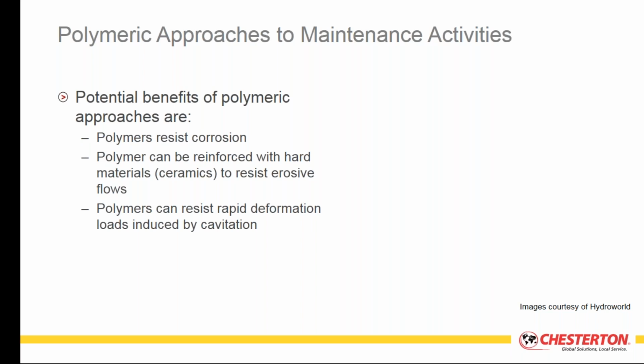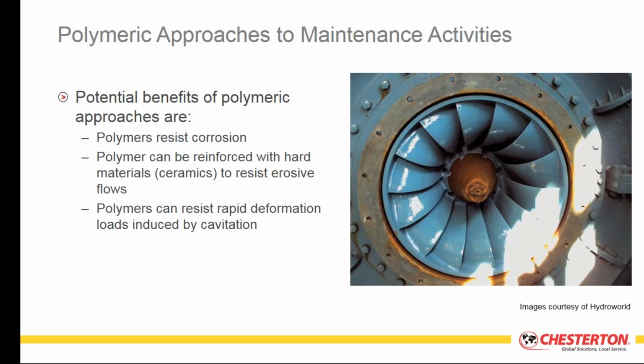However, if cavitation is relatively slow and progressive, you may be able to use a polymer-based compound quite successfully to address and repair those zones of cavitation, with the understanding that when you come back on a maintenance cycle 3 or 5 years later, you may need to do some more touch-up to those areas. Here are some examples of polymer-based coatings on hydro runners.